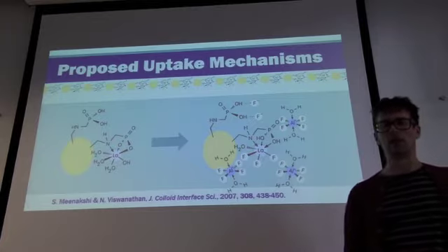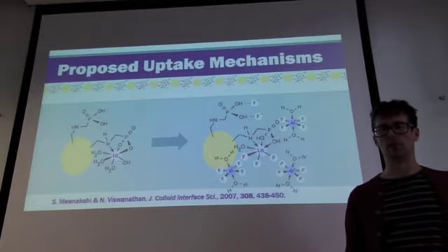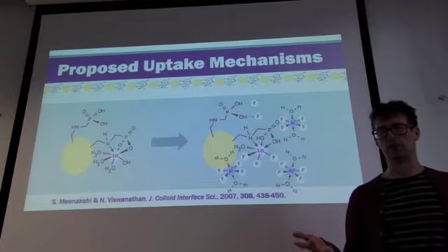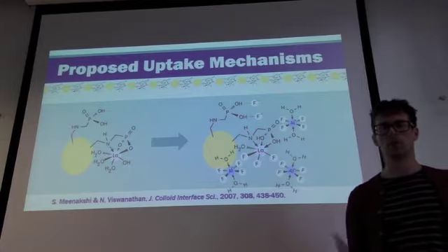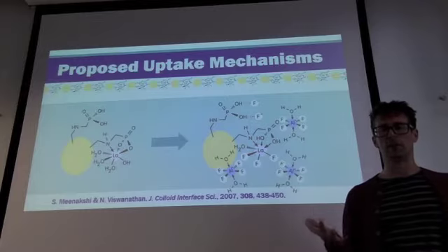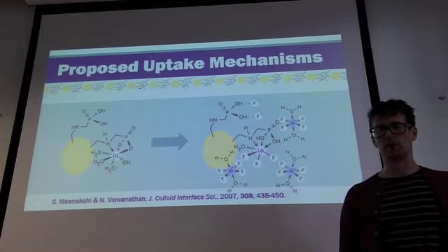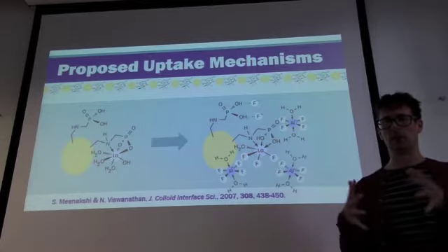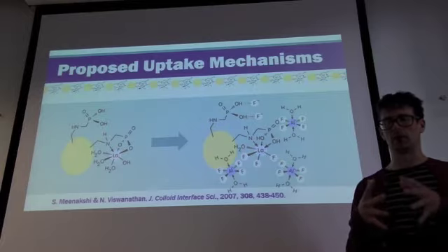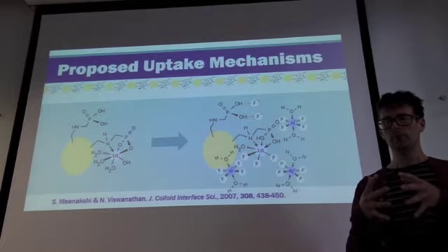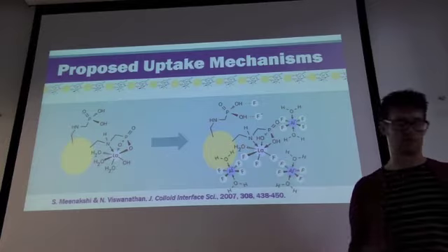Again, we've calculated an estimate for the number of moles of aluminium that are transferred onto the resin during contact. We know that the aluminium doesn't push the lanthanum off the resin, and there are nowhere near enough vacant coordination sites for this to explain the data. So the only logical conclusion is that individual layers of aluminium and fluoride complexation are forming on the surface of the resin beads.